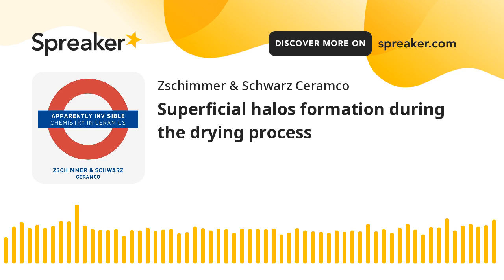If the problem persists, even in case of a proper setup of the dryer, a chemical intervention is necessary, so as to eliminate the problem at its roots. In this regard, for example, it could be important to study and check the dispersant agents used in the grinding phase. Why? Just because most of these chemicals are based on sodium silicate, a chemical compound completely water-soluble, and that, as we already saw, represents one of the origins of the problem. So, we are saying basically that the choice of the dispersant that has to be used is very significant.